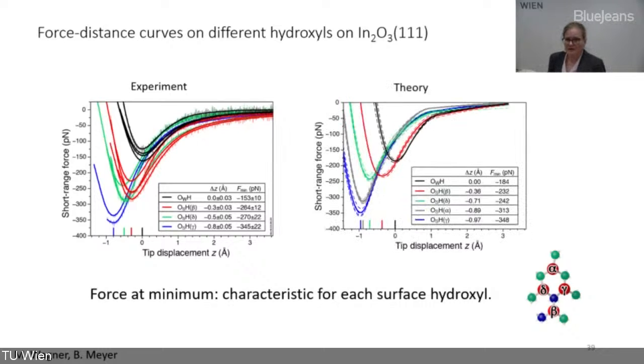Not only could we see this in experiment, we could model it really well with theory too - there's quantitative agreement between theory and experiment. You can measure the force between one OH on the surface and one OH on the tip and get quantitative agreement with theory.